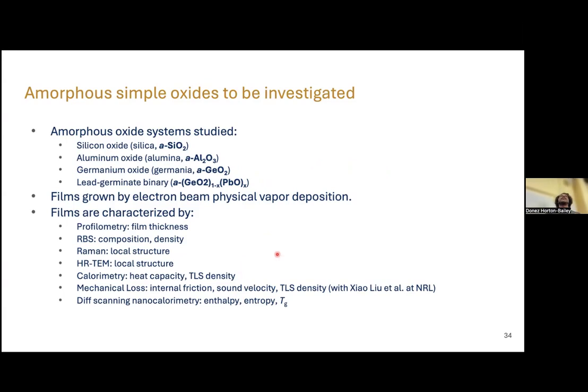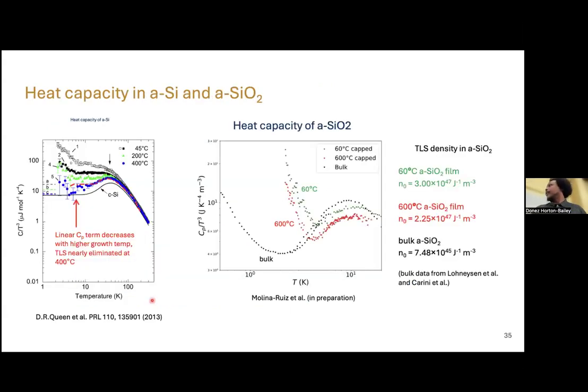So this is how we know that we actually have what we think that we grew. If I grow SiO2, I should have 33% silicon atoms and 66% oxygen atoms. And so we have various tools like Rutherford backscattering spectroscopy to verify that composition. We have different ways of understanding the structure, different types of Raman spectroscopy, high-res TEM. We do calorimetry and other ways of actually measuring the TLS density as well.